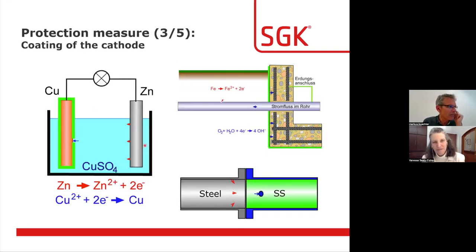So what is effective is that you coat the cathode. So you coat the copper, you decrease the copper surface here, that decreases the corrosion rate on the zinc, and that decreases the total current consumption, and that will prevent corrosion. So in this configuration, that would mean you leave the steel bare and you coat the stainless steel. Now explain that to a customer. But I had cases where I insisted on that because it was the only way to actually prevent the issue.